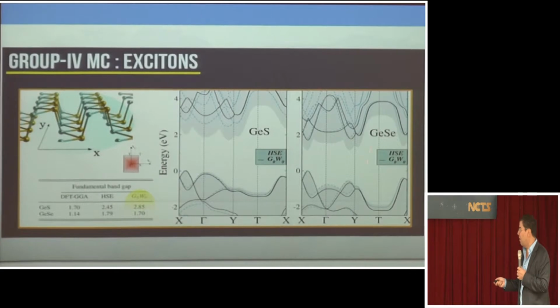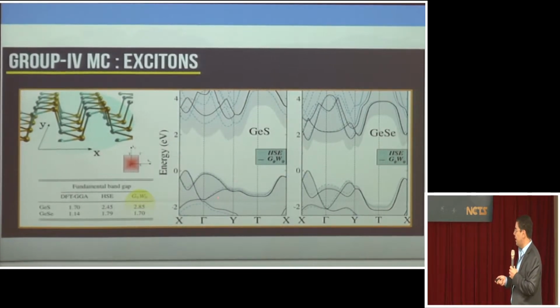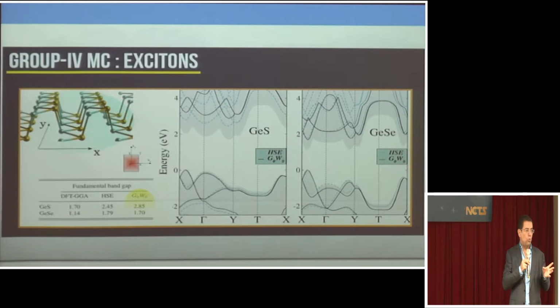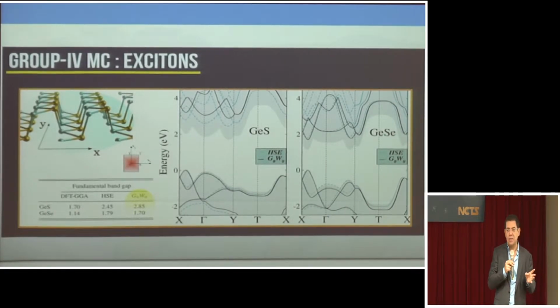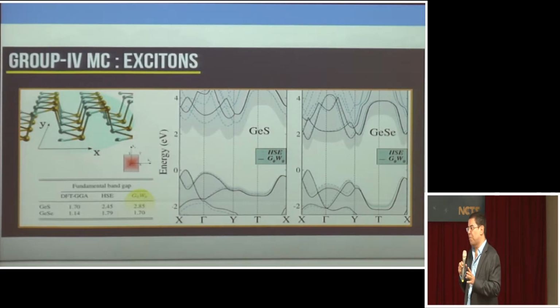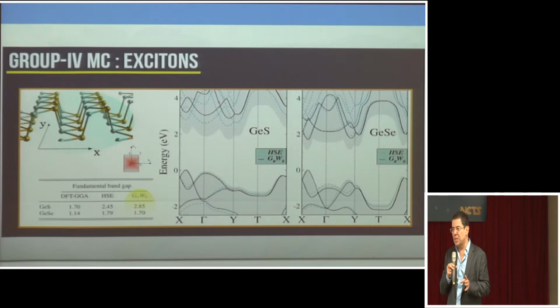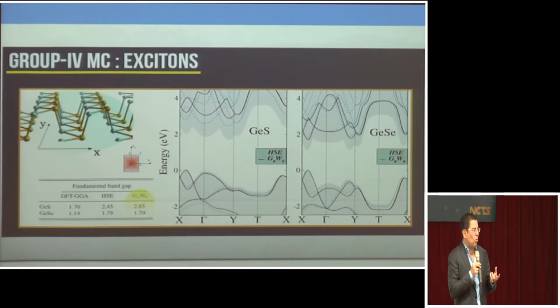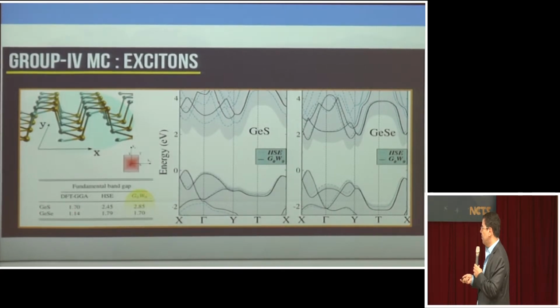So this is an example of excitonic calculations. This is for germanium selenide. And one thing that we realized is that in these materials, if you really want to do a good calculation of exciton binding energies, you have to go beyond traditional numerical approaches. You have to do more complicated calculations like what's called GW. It's a self-consistent calculation that puts the electron-electron interaction into the calculation at a higher level. Okay? So, for instance, this is a traditional DFT result for the band gap. If you do DFT for germanium sulfide or selenide, the gap is, say, 1.7 eV, but GW brings it much closer to the real gap, which is 2.85.